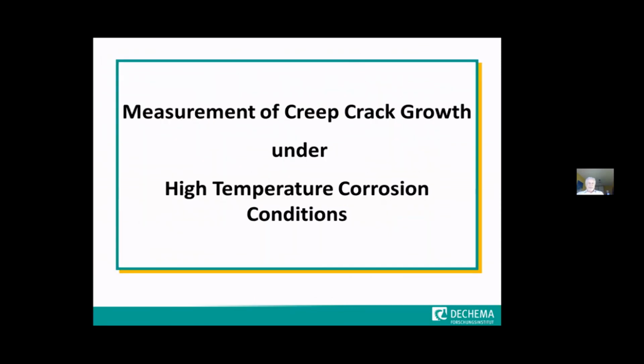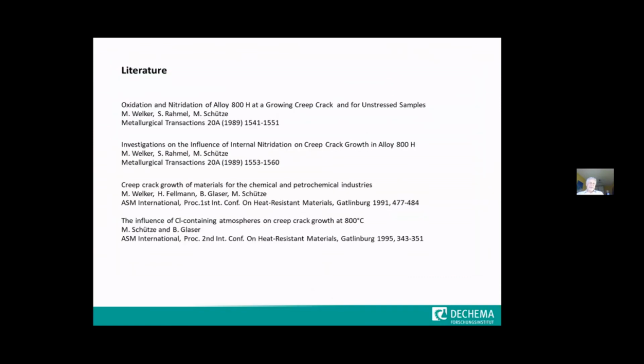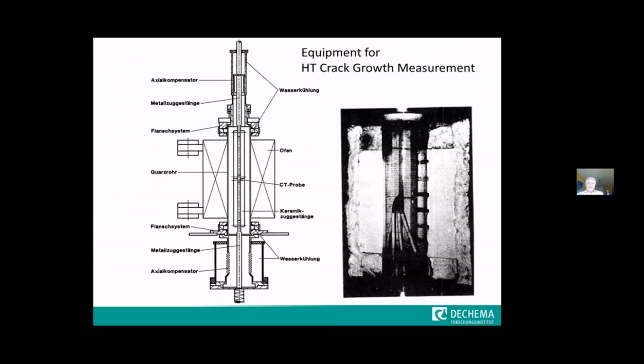So, and then let's switch to the end of life, which means to the growth, to the corrosion-induced or corrosion-assisted crack growth in a material under high temperature corrosion conditions. And again, there's a couple of papers that I would recommend to read. These papers go back until the first one in 1989. And so this is also the reason why this photograph on the right side is not the best one.